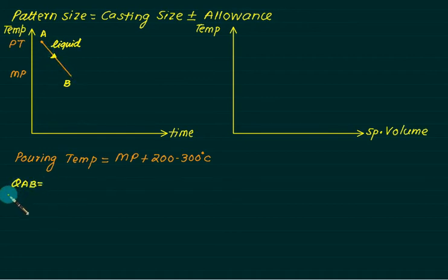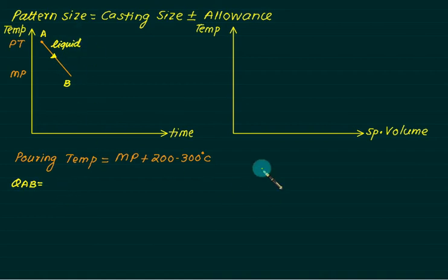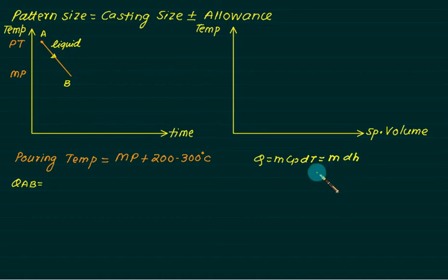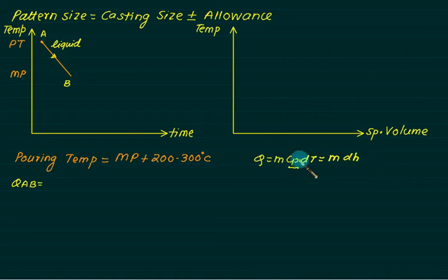Q is used for heat. Heat lost here — is there a phase change or no phase change? No phase change. Normally Q is given by m·Cp·dT when there is no phase change, and by m·dH when there is a phase change. Once there is a phase change, we cannot define Cp. So the equation Q = m·Cp·dT should not be used for phase change. But you can always define enthalpy whether there is phase change or not.